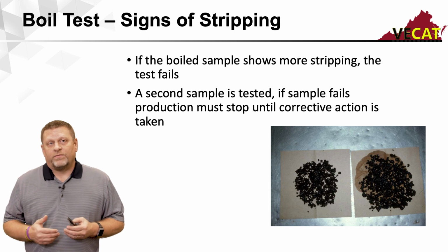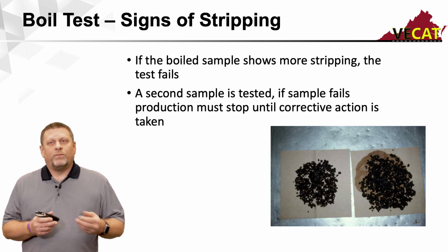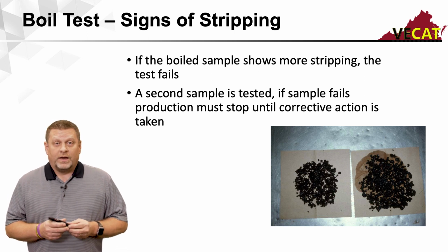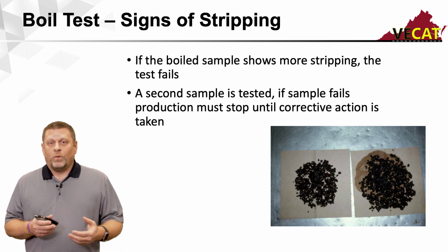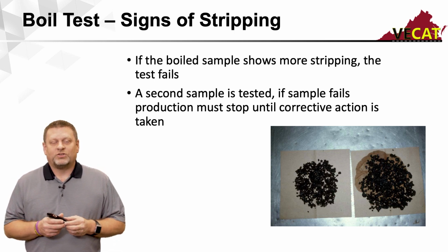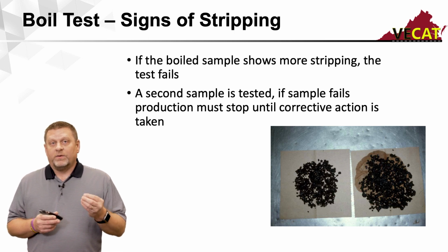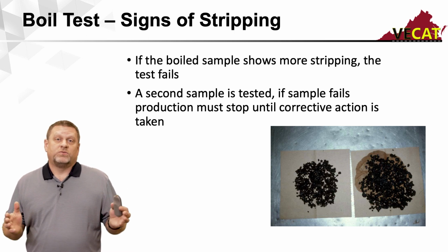I can also tell you from previous experience, another part of my past career was I was with a producer, and I used to make asphalt. And of course, everybody's trying to sell me a new snake oil, a different anti-strip additive. This boil test is a quick way to screen the potential of a different anti-strip additive on your mix without taking 4 days to do TSRs.